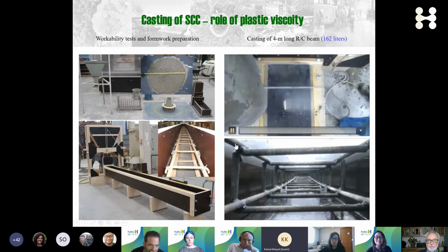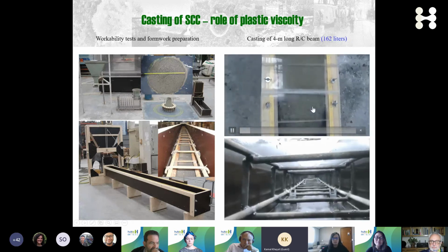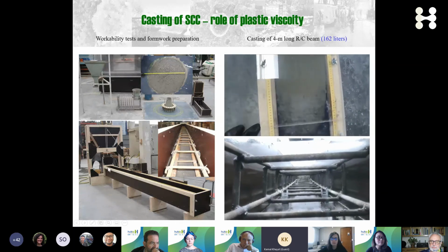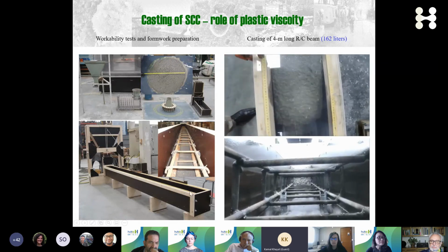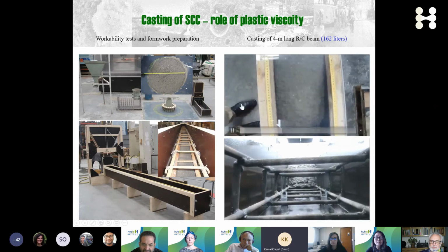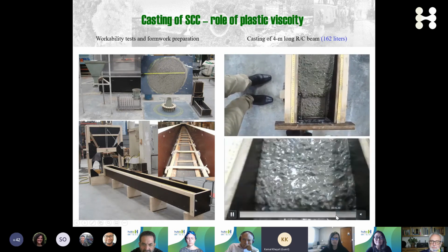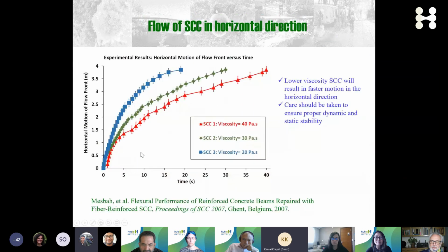And here I'm going to just quickly show a video of placing SCC, and you can see on the upper curve is the upper view of this casting of this reinforced concrete beam that measures 4 meters in length. It's cast using SCC of different viscosities. And the lower the viscosity is, the faster the concrete is going to flow. Okay? And we can see here the flow, where it reaches the front versus time, and you see that it reaches 4 meters after 20 seconds if the concrete has a 20 Pascal viscosity. Otherwise, it would take 40 seconds to reach 4 meters if the concrete has 40 Pascal viscosity. Both of these concretes have the same yield stress, so adjusting the viscosity is very important for productivity. At the same time, we have to be careful about the stability of the material so it does not segregate.